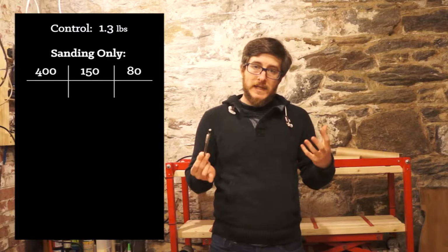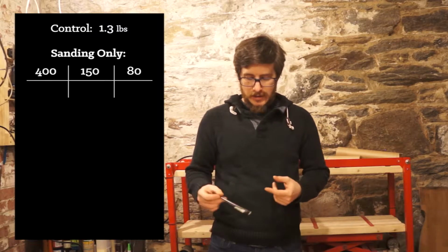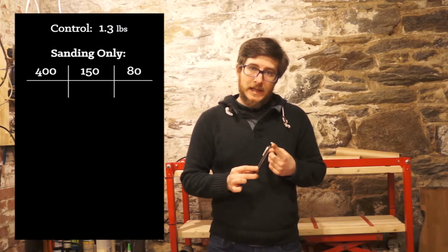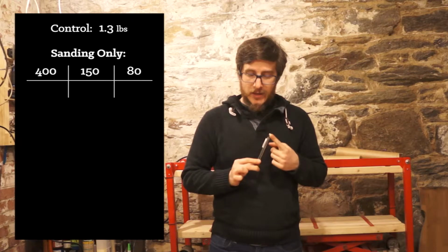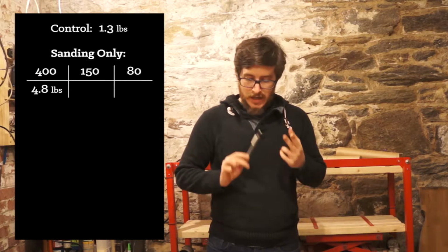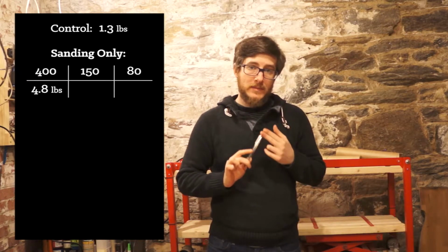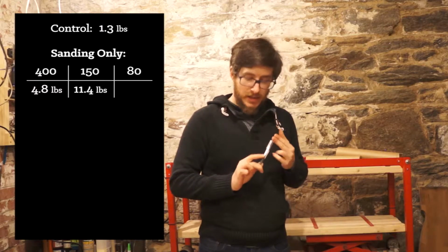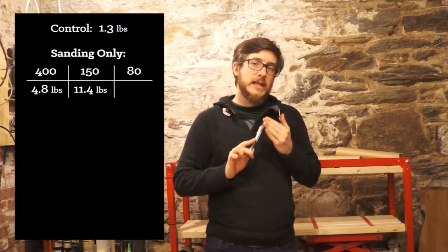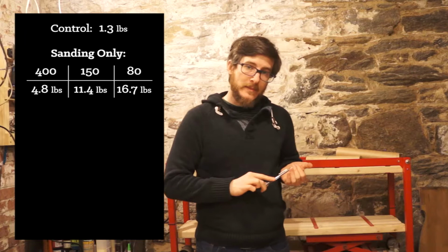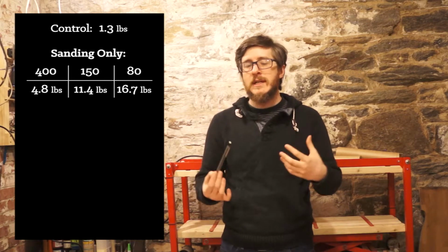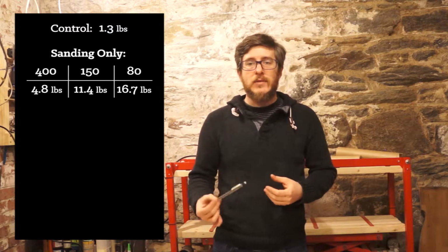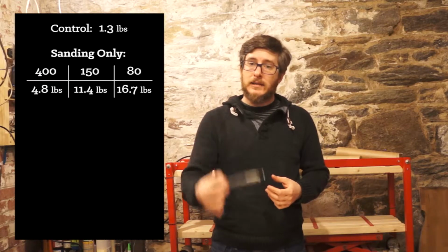For the set of samples that were not flame treated, the 400 grit sanded sample peaked out at 4.8 pounds. The 150 grit sample peaked out at 11.4. The 80 grit sample peaked out at 16.7, which seems to indicate that if you're just sanding, a coarser grit is going to get you a better bonding strength than a lighter grit.